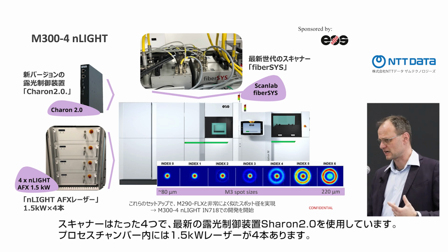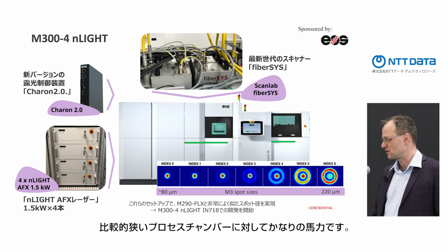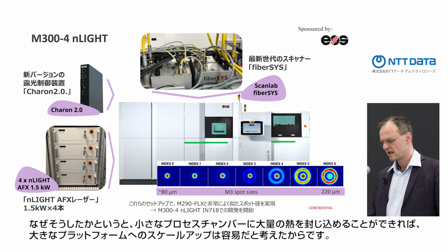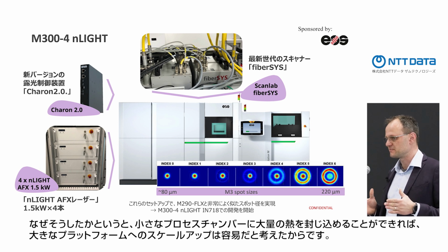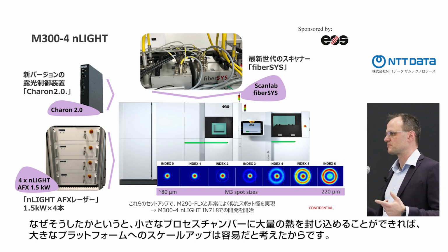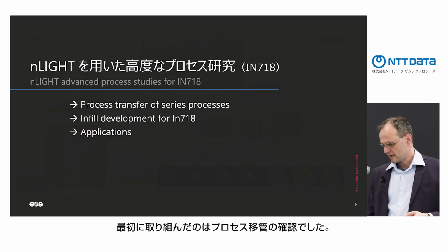And we had 4 times 1.5 kilowatt of light inside a very small process chamber. So this is a lot of horsepower in such a relatively small process chamber. Now, why did we do that? We think that if we can encapsulate so much heat in a very small process chamber and we can manage to tame the beast, it's an easier thing to scale up onto bigger platforms.